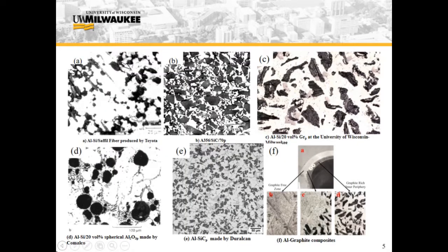This slide shows the kind of microstructures that can be produced in cast metal matrix composites. In the aluminum silicon alloy and ductile iron alloys, the ratio of the reinforcement to the matrix phase is restricted by phase diagrams and thermodynamics, where you are limited in the kind of composites you can make. In the composites that I will talk about today, we add particles or fibers from outside into the melt, so there is really no limitation of the different kinds of microstructures I can produce.